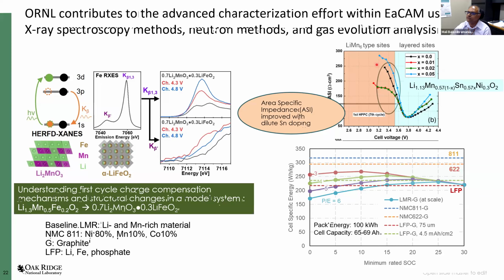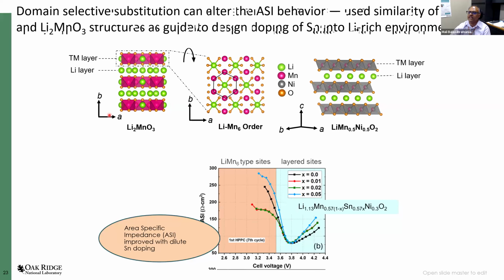So this is how it looks. You have these Li2MnO3-like domains, and you have these layered regions. This is a schematic of it. And what we wanted to see is whether there is a way we can selectively dope the Li2MnO3 and see if it affects the performance or the behavior of this material. One of the first things that we chose was tin, because we know that Li2SnO3 has a very similar structure to Li2MnO3, and both tin and manganese are 4-valent. So we believe that we should be able to do some doping of manganese sites in this material, and we used this as a guide to design this.